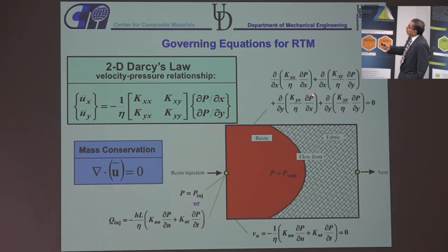And then what you're doing is applying this equation with the boundary conditions and solving for the pressure in here. The problem is that it's a moving boundary problem, so at each time step you have to change your domain because more resin is coming in, and then you have to resolve the problem. So what we do is solve it as a steady state problem at this time step, then advance the flow front once you know the pressures, and then resolve it as a steady state problem.